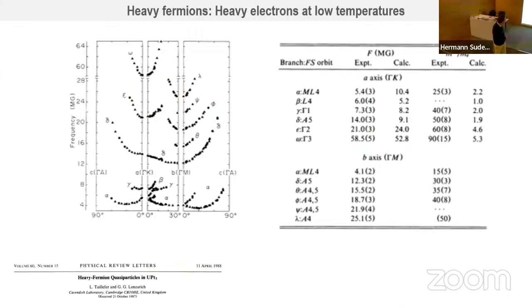I think this experiment has been made at high magnetic fields. So this is the measurement of the Fermi surface. And this experiment shows you that in this material, which has F electrons because of the uranium, you can actually obtain the geometry of the Fermi surface. And the geometry of the Fermi surface has been measured in full. Okay, so all bands are contained within these measurements.